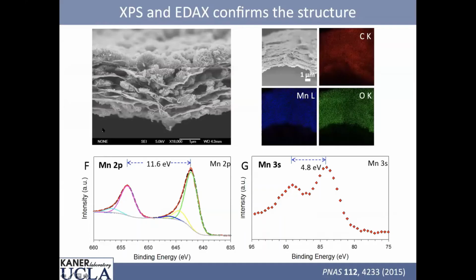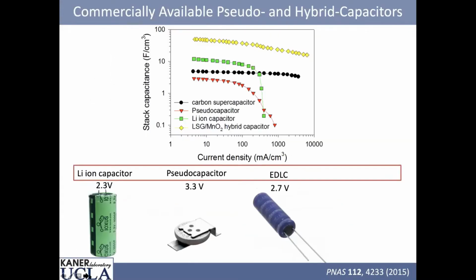All right, let me show you the results. If you look at this, you can see the graphene that's produced, and these things that to me look like cauliflower, that is the MnO2. We can look by photoelectron spectroscopy, and you can see the carbon, you can see the manganese, you can see the oxygen, so it's completely throughout the material. And we can even demonstrate that it's in the correct oxidation state. We have the correct form of manganese dioxide. And when we look at these, we get very high capacitance, higher than anything that's been seen.